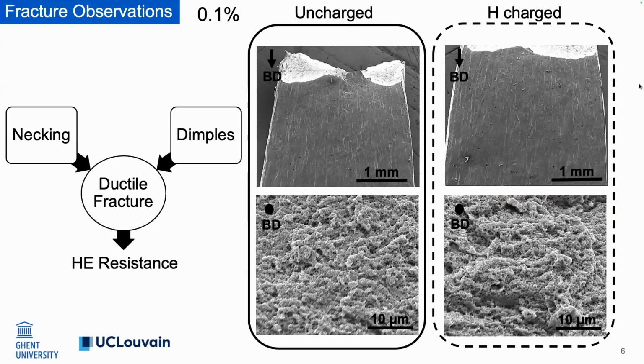Okay, this is the fractography of material with lower porosity fraction. You can see in the images above, after charging, necking is obvious for both uncharged and charged conditions, and in the fracture surfaces we see dimples are present. So the fracture mechanism of this material is ductile, and this corresponds to small changes of ductility after hydrogen charging and the hydrogen embrittlement resistance of this batch.